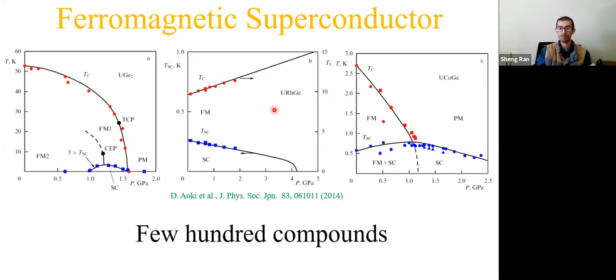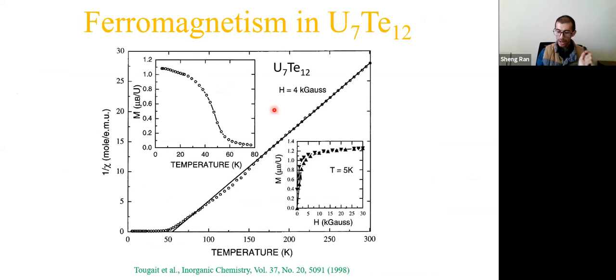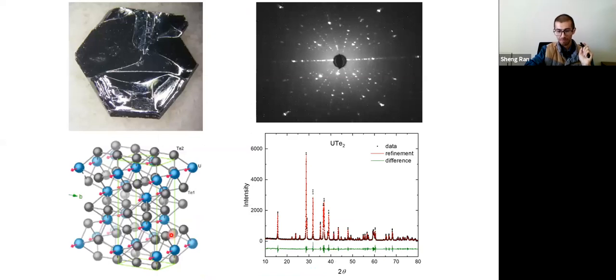That is doable. We actually looked at many ferromagnets containing uranium. For example, uranium cobalt aluminum and a few other compounds. And this time, the target was uranium-7 tellurium-12. So this is a ferromagnet. You can see the Curie-Weiss temperature is about 50 K. So, let's make it.